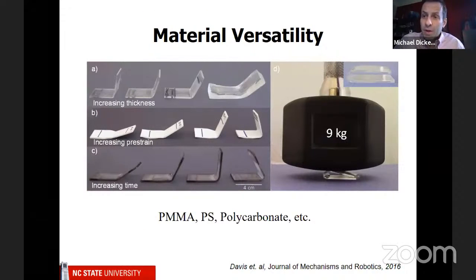So we've done this mostly with polystyrene, which we use because it's commercially available, but we've also done this with different polymers. This is a polymethyl methacrylate. It's acrylic, polystyrene, polycarbonate. These are all different, very common polymers. And the key idea, again, is that the materials have to be stretched. We've done it with different amounts of thickness, different amounts of strain, and different amounts of time. And you can see that if you use a polycarbonate material, like a material that would be used to make an airplane window, very tough, not going to break, very strong, it can withstand quite a bit of force.